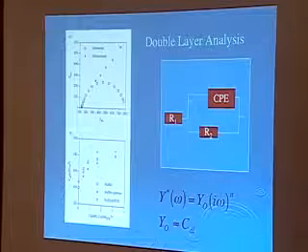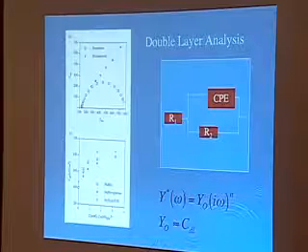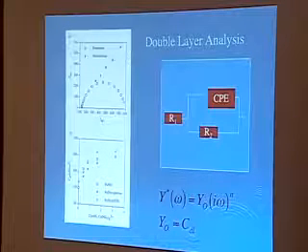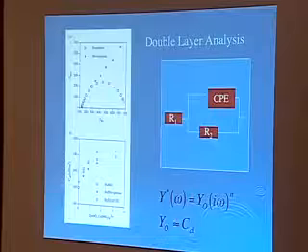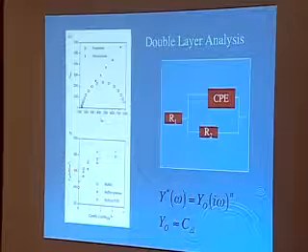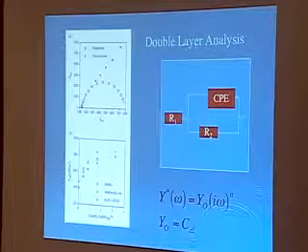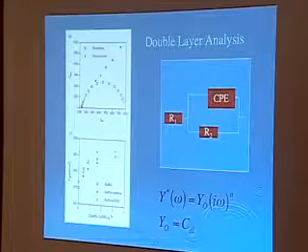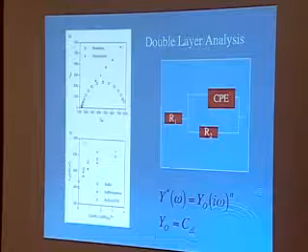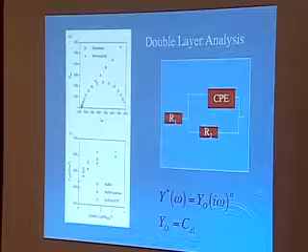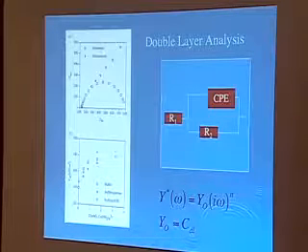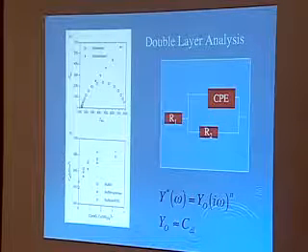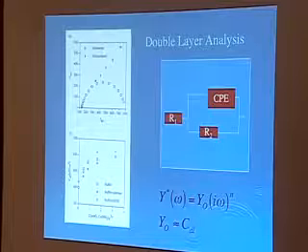So we fit it to this simple circuit since that's all we're after. And we have a good fitting program to do this. It's a nonlinear least squares. So that's the semicircle that you get out of that fit, by the way. And you see that independent of whether you have buffer around or enzyme or things like that, and we're doing this as a function of the cobalt hexamine concentration, which of course makes the things work better, that while there is some change in capacitance with concentration, it's modest.